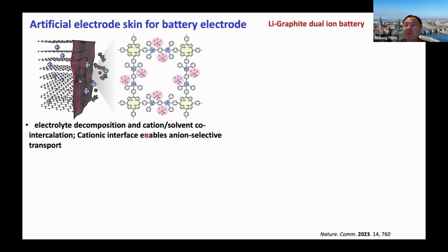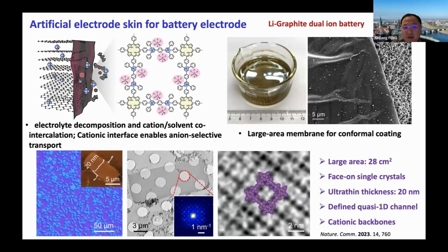The question is, how can we be more selective without having intercalation of cation and the solvent? Because these end up with electrolyte decomposition. So here the idea is we put in an ultra-thin membrane, without sacrificing the energy density, that can block the cation and the solvent, with only selective intercalation and transport of anions. And this is where we use this 2D polymer, crystalline thin film. We can make it over large areas, with a thickness of a few nanometers to 10 nanometers. They have well-defined 1D channels, and they have a cationic backbone, which is very good for anion selectivity.